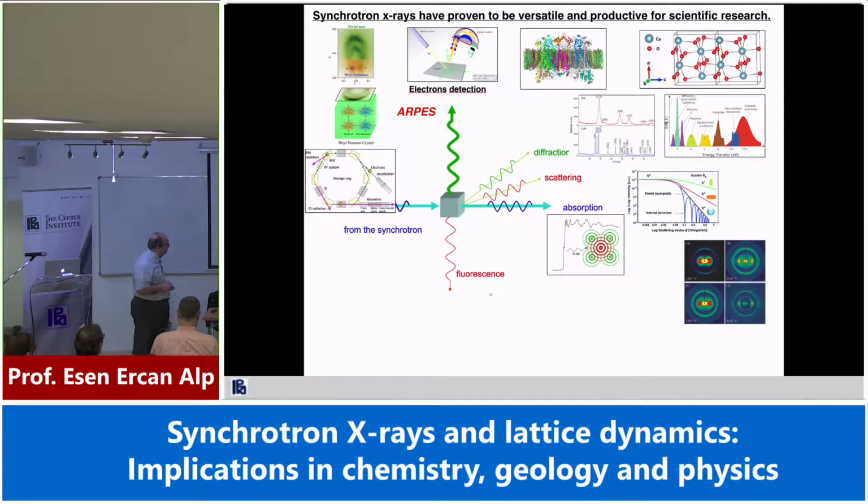And you can also do something called X-ray absorption spectroscopy, which most of you are familiar with, XAFS or EXAFS, to look at... This is a method where an electron is knocked out, and now your electron becomes your probe because it scatters from the nearby atoms, which gives you these oscillations, and then you take the Fourier transform of these oscillations to find out about the first, second, third near neighbors. And the information in the near edge gives you quite a bit about the valence state and the coordination number of the